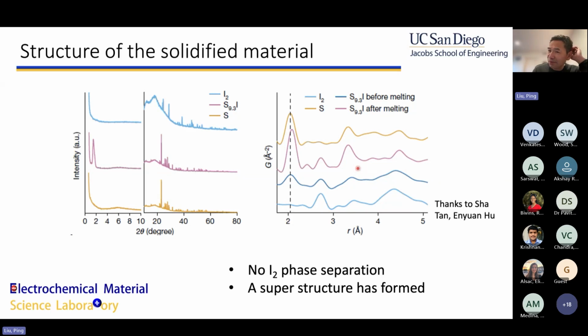People always thought sulfur and iodine do not react. They form a eutectic. If you recall the definition of a eutectic, you mix two solids together, the melting point is suppressed. However, when you freeze the liquid, the two materials will go back to what they were. That's not what happened here. Instead, we discovered in X-ray diffraction a peak at a very low angle. What does this mean? This means sulfur and iodine form a mesostructure with a repeating distance on the scale of nanometers.